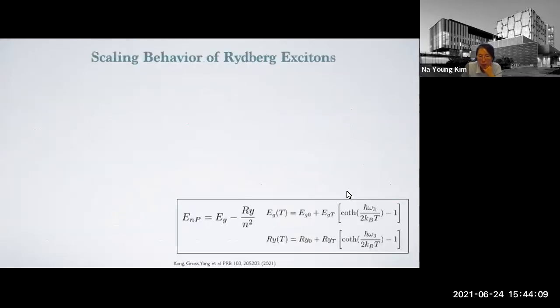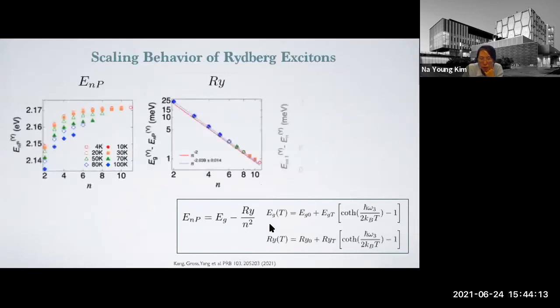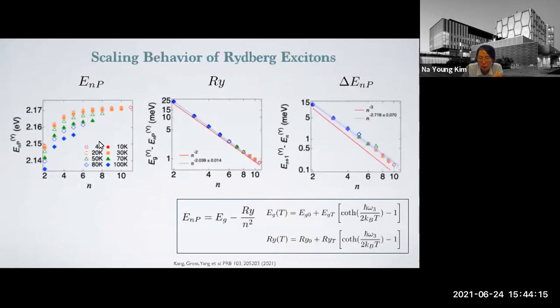Now let's see what kind of scaling behavior the Rydberg exciton shows in terms of temperature. These are the relevant energy states. We are very excited to have a universal behavior of the bound exciton. The binding energy is proportional to 1/n squared, so this is the 1/n squared scaling law. And then the energy state difference, the level spacing, goes as 1/n cubed.